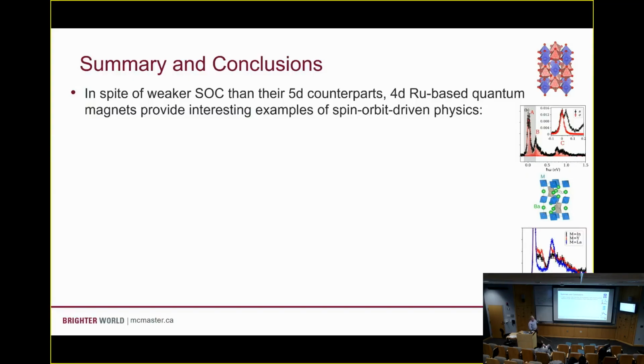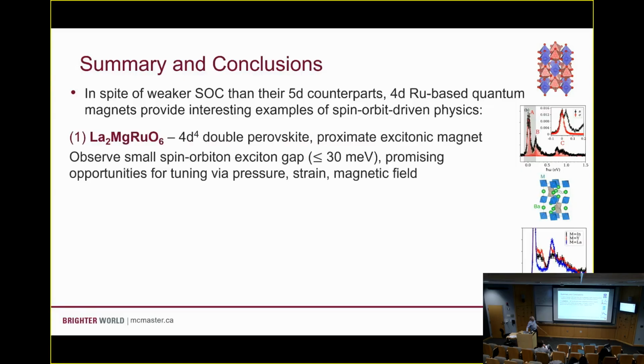And so the punchline here that I'd like to leave you with, when we think about where interesting spin-orbit physics is found, I'd make the case that even though there's less spin-orbit coupling to work with here, these 4D transition metals can actually be as interesting or more interesting because they give you a set of materials that are more easily tunable. Okay, so you get spin-orbit entangled states, but ones which are much more flexible in terms of the kind of perturbations that we have to use in the lab.